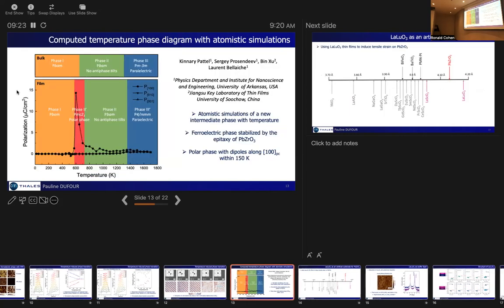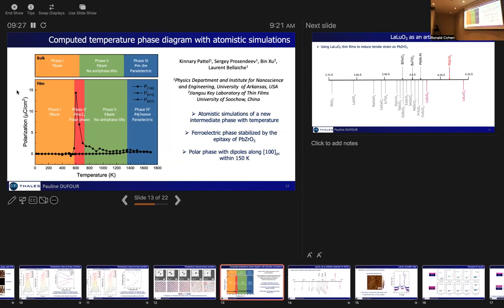So our experimental observations were supported by atomistic simulations led by the team of Laurent Bellaiche, where they implemented in-plane compressive strain similar to what we observed in our films, and they predicted the emergence, due to this compressive strain, of a polar phase within a temperature range of 150 K, which is similar to what we observe experimentally. Interestingly, both our experimental observations and their simulations suggest an orthorhombic structure for this polar phase, in contrast with the usual rhombohedral R3c symmetry that is expected and that was observed in the intermediate ferroelectric phase in bulk PbZrO3. So we need to further investigate the structure of this polar phase to determine exactly what it is.